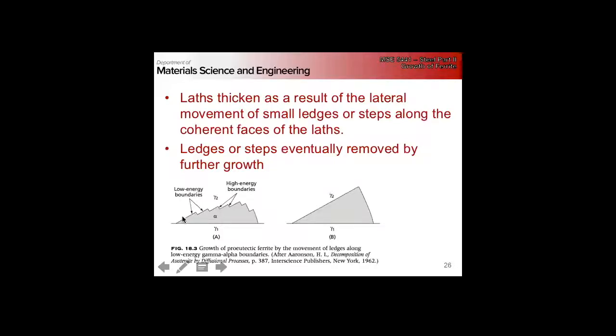We don't have much mobility orthogonal to this direction, but if our interface is made up of these steps, we have these high energy interfaces with high mobility, so it can grow by extending the ledge, all of these ledges this way.